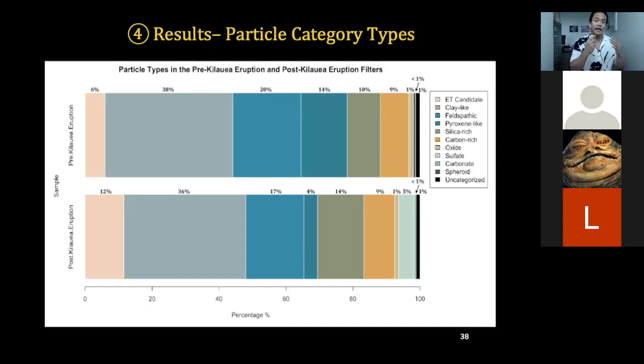The first being the ET candidate percentages. Again, 6% for pre-Kilauea, 12% for post-Kilauea. There's also a huge disparity in the pyroxene-like category, 14% for pre-Kilauea and 4% for post-Kilauea. And then finally, the post-Kilauea eruption filter showed approximately 5% sulfates, and we weren't able to find any sulfates at all in the pre-Kilauea eruption filter.